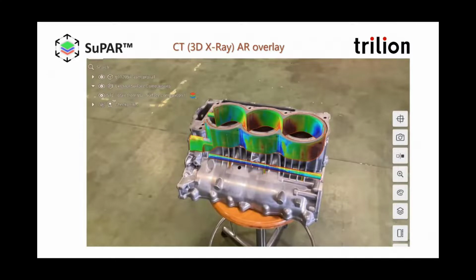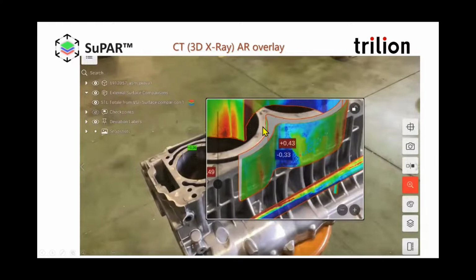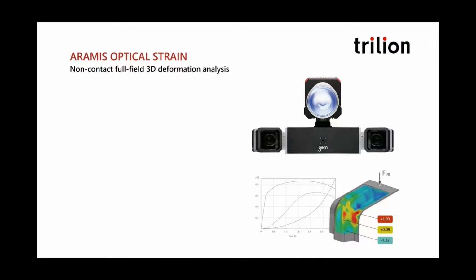In this case, we took our CT and we're overlaying the CT right onto the part sitting, as you can see, on a stool. But you can see the CT data. Zoom in on it, and you can actually document where the problems are, if there are any, and what the dimensions are from the CT measurements that we did. And so it just becomes this integrated tool as part of our optical metrology capabilities.